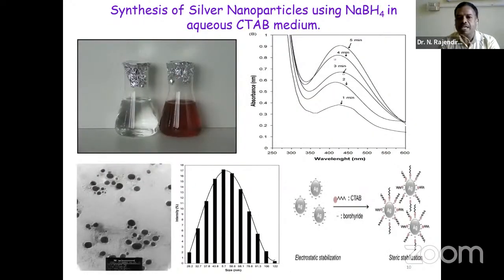So this is one of the examples for the preparation of metal nanoparticles using a surfactant, where they used CTAB. That is, CTAB is the cationic surfactant, cetyl trimethyl ammonium bromide, the stabilizing reagent, and they add sodium borohydride to silver nitrate. So after the reduction, what will happen? The CTAB covers the surface of the particles, so that in that manner the particles are stabilized or the growth of the size is controlled.